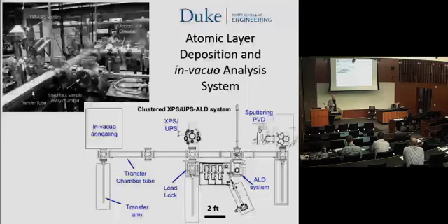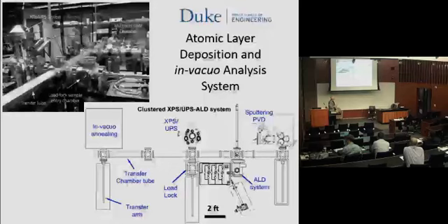And we can grow any kind of carbon nanostructure on any one of these electrodes that we choose to. We also have atomic layer deposition, and an interesting analytical system connected to it, for X-ray photoelectron spectroscopy and ultraviolet photoelectron spectroscopy. The ALD system can grow materials in atomic layer by layer fashion. And the analytical system is surface sensitive, so it can analyze them in atomic layer by layer fashion. The important part is that it's connected in UHV.